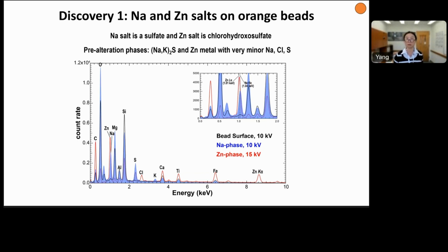So the sodium salt and the zinc salt are altered products from the condensate. Because we didn't use water or any other liquid, the ratios of elements such as sodium, sulfur, or zinc to other elements, except for oxygen, we believe are kept. So we can use the elemental chemistry to infer what the precursor phases are. With that information, we derived that the sodium salt is actually a sodium potassium sulfide, and the zinc salt is mostly zinc metal with a very minor amount of sodium, chlorine, and sulfur.